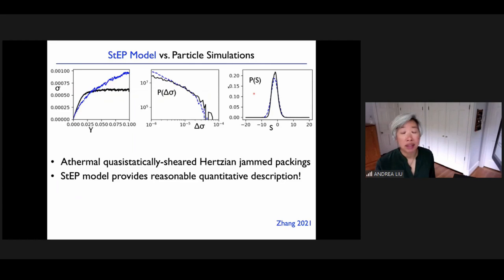So this is the particle-based simulations that I showed you earlier, ductile case, and here is what we see in the step model. And you see it looks really quite similar, that you have these localized rearrangements that can jump around and appear far away. So qualitatively, it looks very similar. Quantitatively, it's really very good. So here's the stress-strain relation. The black are the particle simulations, and the blue are the results from the step model. And this is the distribution of stress drops, so the avalanche size distribution.